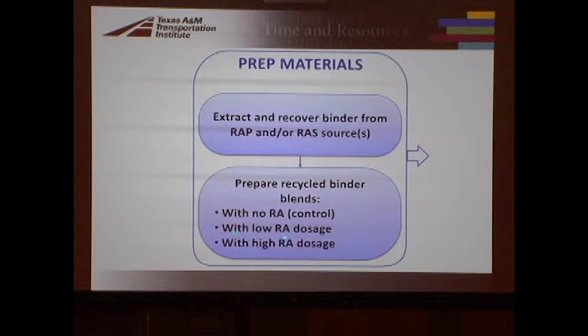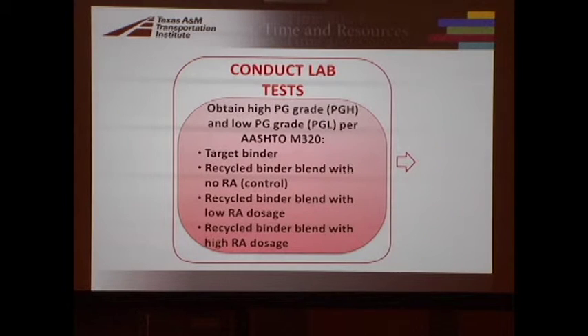So we look at 2% because we thought that was a pretty low dosage, and then we look at 10% because we thought that was pretty high. Well, we thought that was pretty high until we started looking at the material combinations that we used. But even so, we do have to extrapolate a little beyond 10%, but we still feel pretty good about it.